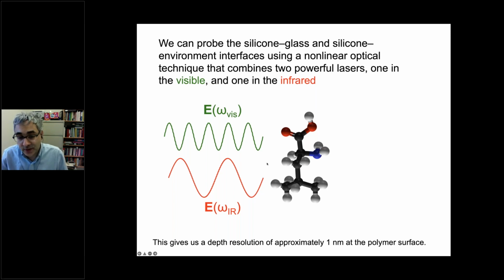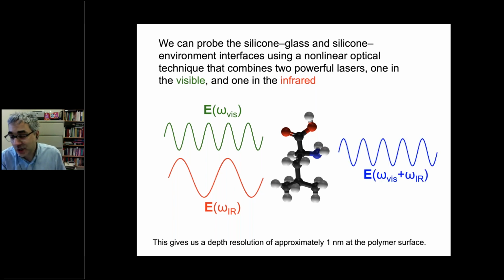And if those photons are annihilated, there's two laws of nature which must be observed. One is conservation of energy. A new photon has to be born, and its energy has to be the sum of the energies of the two photons that died. So in other words, we make a new color. That's why this is called three-wave mixing. And if we know the color or the frequency of the visible light and the color of the infrared light, we know where to look for this new light. And the second thing that happens is momentum has to be conserved. So if you know the angle that those two lasers came in at, you can basically understand where to look for this very rare photon creation event.